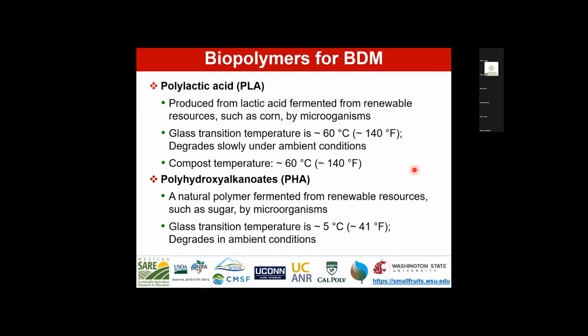Let's contrast polylactic acid, or PLA, to polyhydroxyalkanoates, or PHA. This is a polymer that's fermented from renewable resources such as sugar, also by microorganisms. And it has a glass transition temperature much lower at 5 degrees Celsius or 41 degrees Fahrenheit. And what this means is that this particular feedstock or biopolymer is able to degrade at ambient conditions in the soil.